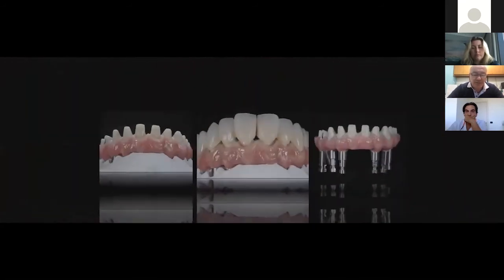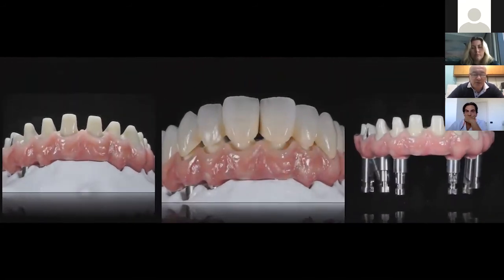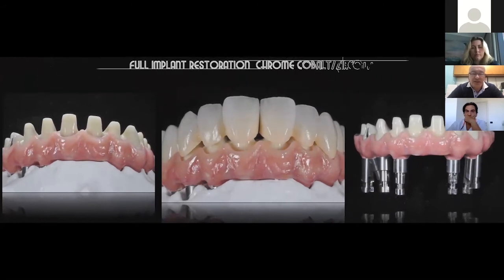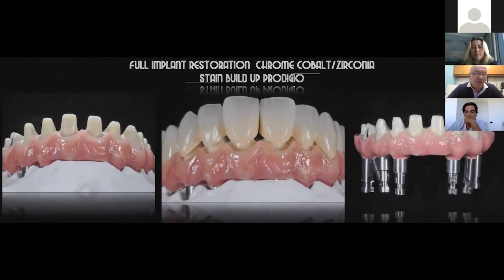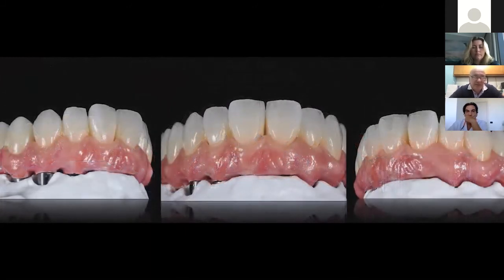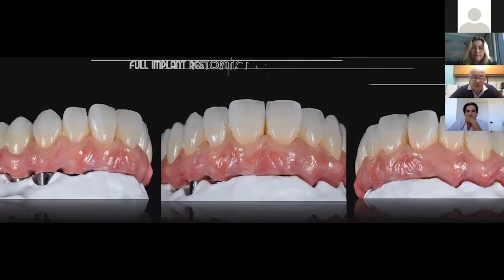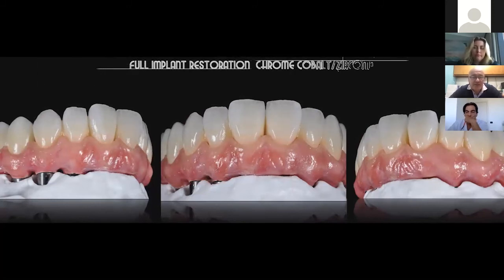This is another, a little bit more complex case. It's a chrome cobalt with a pink porcelain and zirconia bridges cemented on top of this bridge. Why? Because the doctor was a little bit more concerned about using zirconia underneath as a framework, but we are talking here about 15 years ago. This is a case that was done 15 years ago. Here in the beginning in the US, people were a little bit skeptical about using zirconia for a big framework, also because there is a cantilever there.